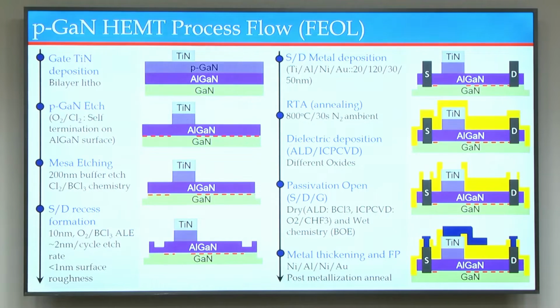And if you leave the pGaN, say if you partially leave the pGaN, again the p-type doping is going to deplete the 2DEG in the access region. So in both cases you are going to lose in terms of performance. I'll also show you later on that there are some other issues because of leaving the pGaN out there. So a selective etch, developing a recipe which is a selective etch, is also very critical.